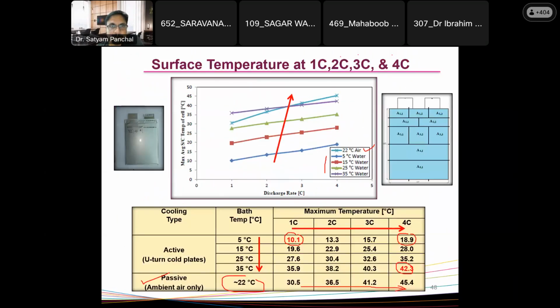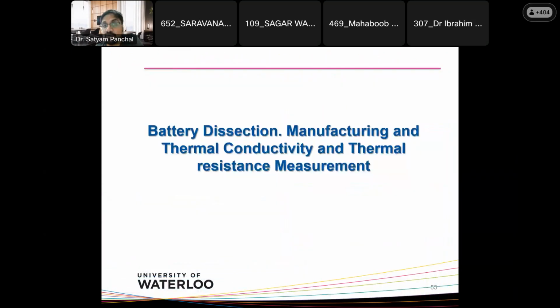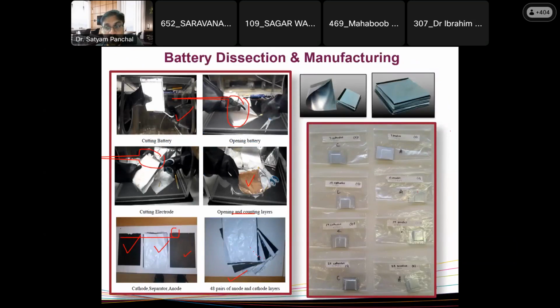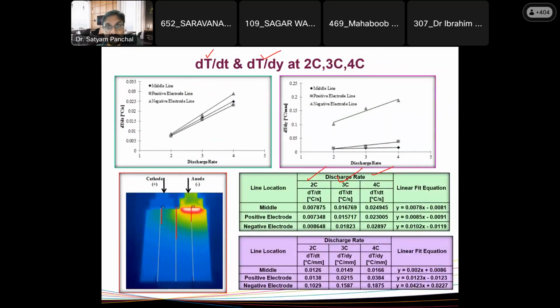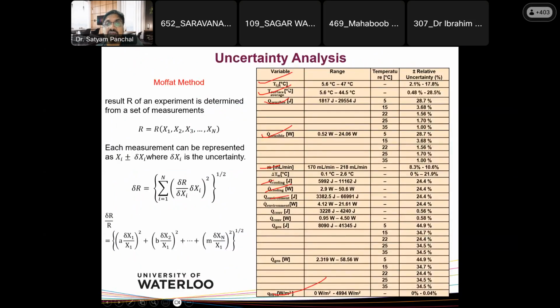Typically, when you do any experiment, we always go for uncertainty analysis, and that is required for your analysis. So this is typical: temperature distribution is around 2%, from 5 degrees all the way to 47 degrees centigrade, then average surface temperature. When you do any experiment, you have to do this uncertainty analysis, and typically we measure relative and absolute uncertainty in percentage. Thank you so much for the wonderful knowledge sharing, sir.